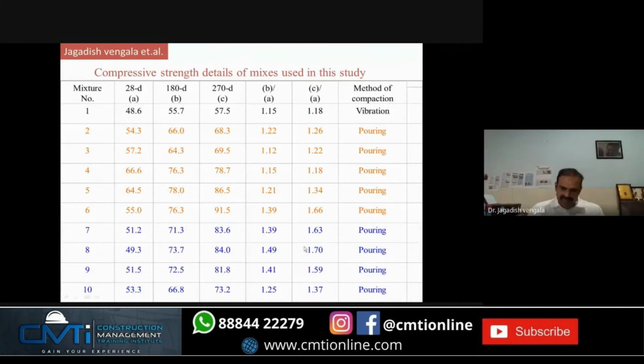Very interesting study, why fly ash. We have actually measured 270-day strength also. That means after 6 months, after 9 months, we measured, when we check the fly ash contribution to the 28 days to 270 days strength.